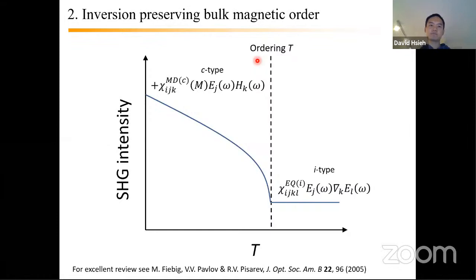So surface magnetization is one way you can get a response in SHG. Another way is, maybe you have some bulk magnetic order that turns on, but it preserves inversion symmetry. In this scenario, you might have some I-type response at high temperatures, let's say electric quadrupole. And then as you go below TC, you now have some C-type bulk response turn on. Let's say a magnetic dipole SHG response that's proportional to your bulk magnetization. So something like this can also turn on an SHG response.